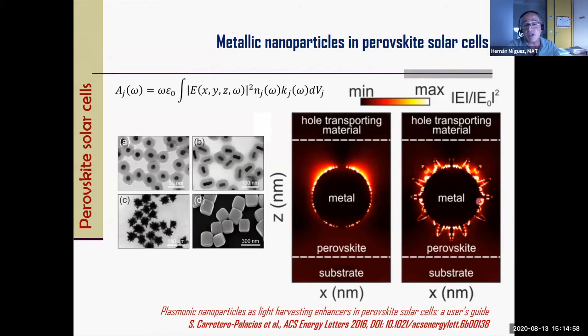of having a metallic particle inside the film. We wanted to take advantage of this near field enhancement I was talking about before to improve the efficiency, right? So we tested every possible metallic particle that we could find and discovered that most of them would have a positive effect, but especially silver nanocubes.